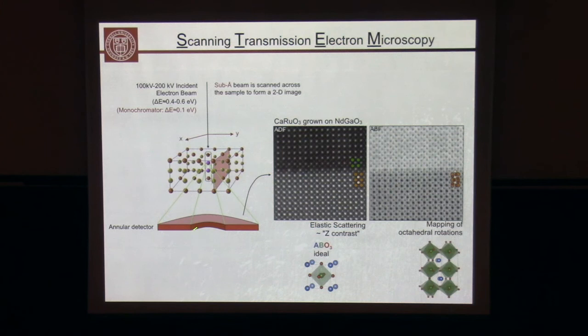closer to the sample. When you do that, you can actually be not only sensitive to the atomic columns that are actually heavy, so high atomic number elements, but also the oxygens. So notice this is the ideal perovskite structure. We have heavy cations at the corners and at the center. So that's the B cation. This is the A side cation. And then we have an oxygen octahedra that surrounds that transition metal in the center.